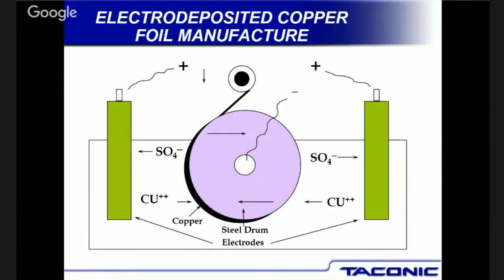Electrodeposited copper is how they're manufacturing at the mill. They have a very, very large stainless steel drum, and what they're doing is bombarding that drum with copper. If you can imagine this drum, there are two sides of the copper. When they manufacture it, there's the smooth side, which is right against the drum. Then there's the outer side, which I call the Himalayan mountains, because it has very large peaks and valleys in the copper. Again, they roll it up, ship the roll to us, and we take it and sheet it.